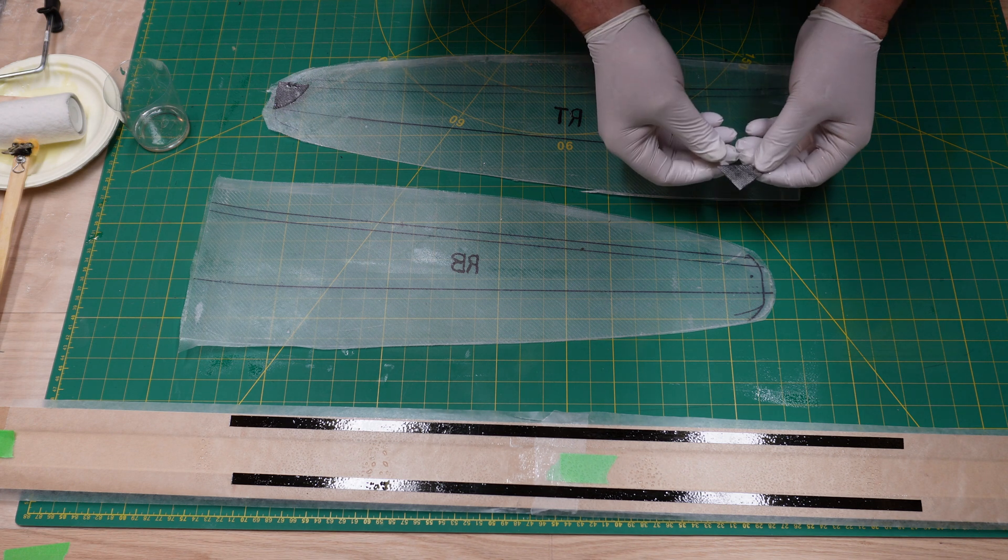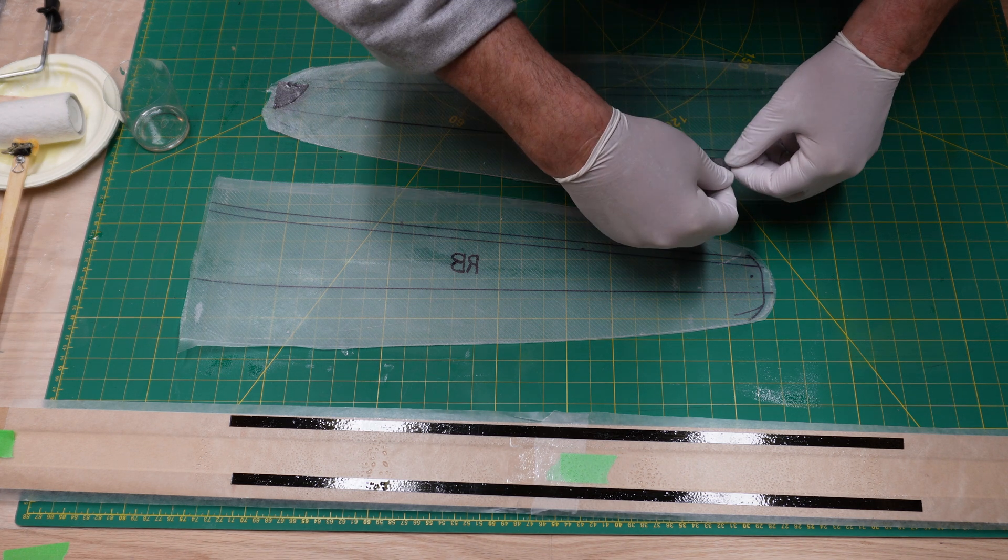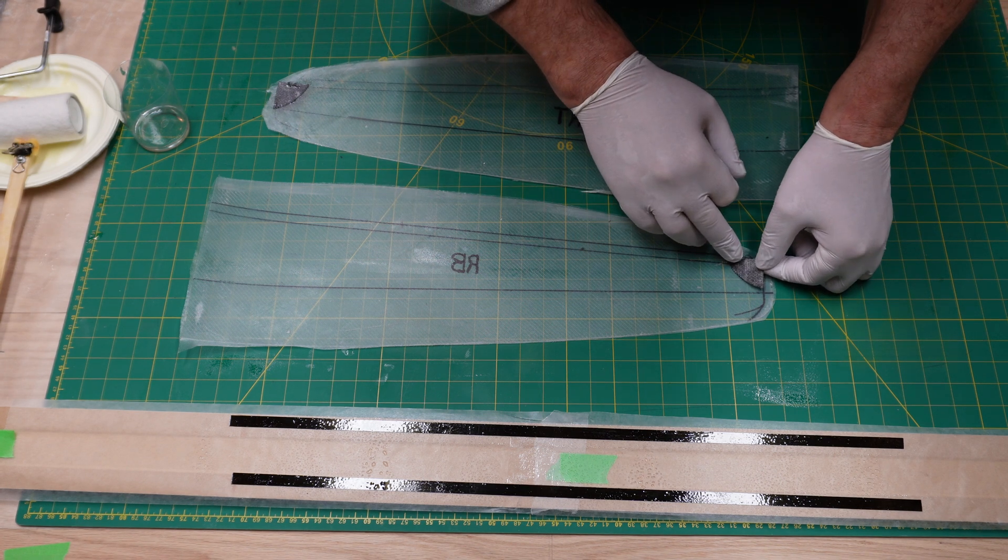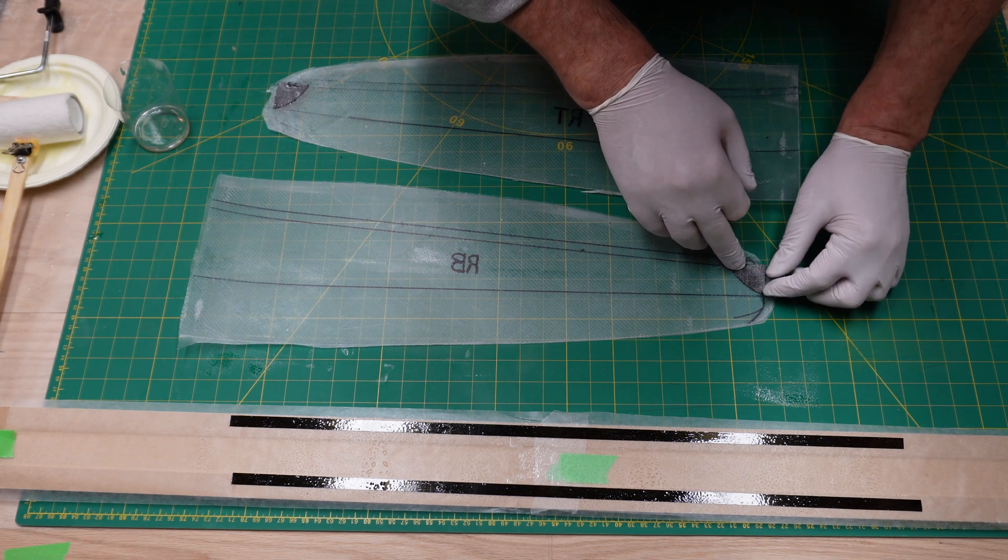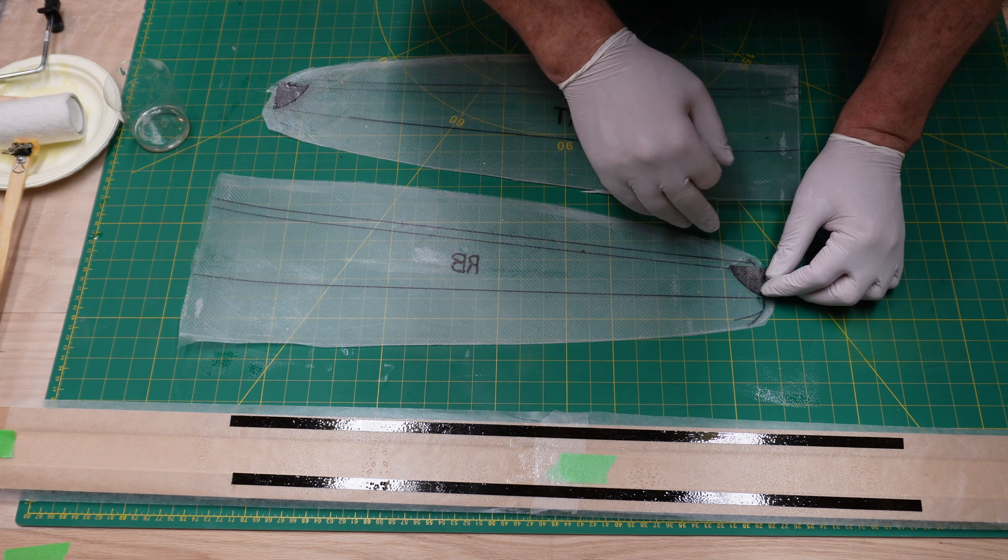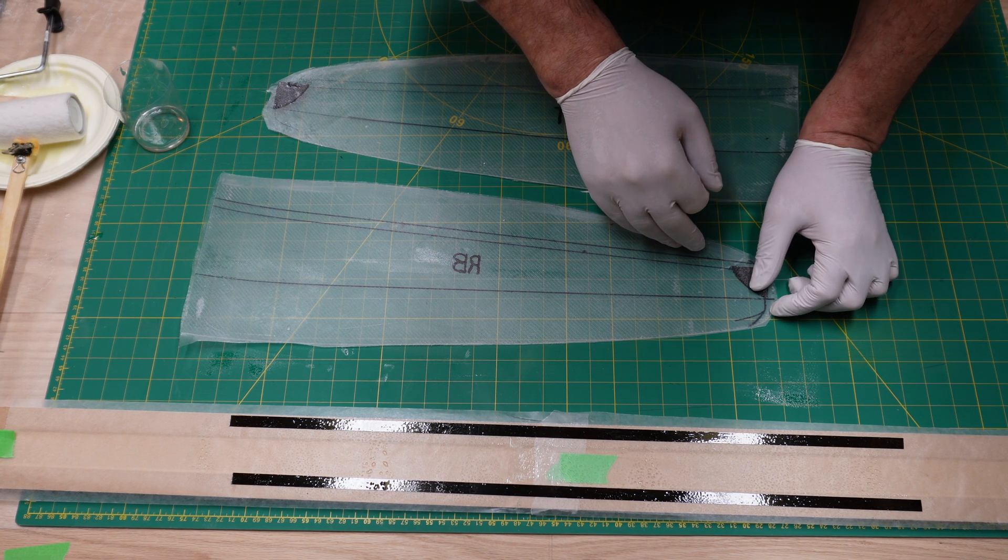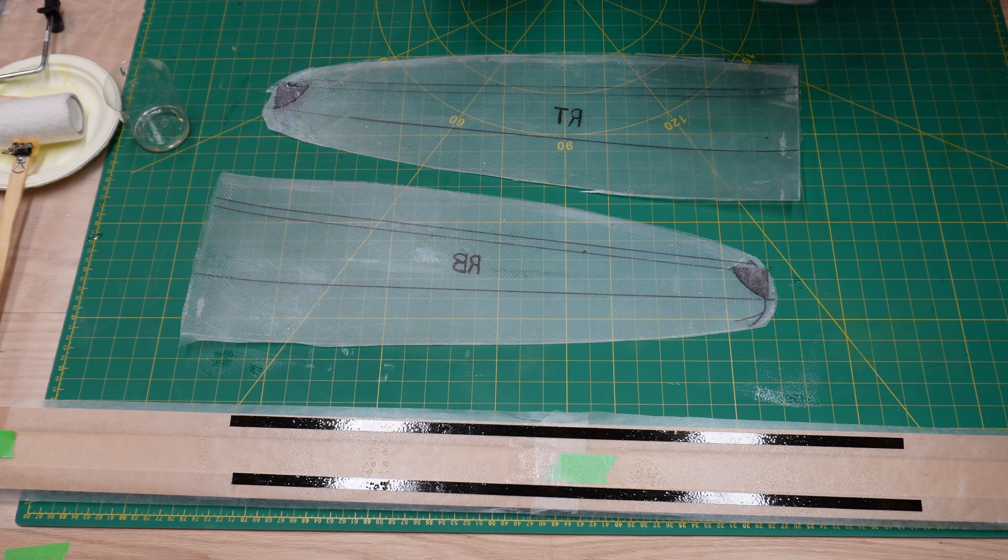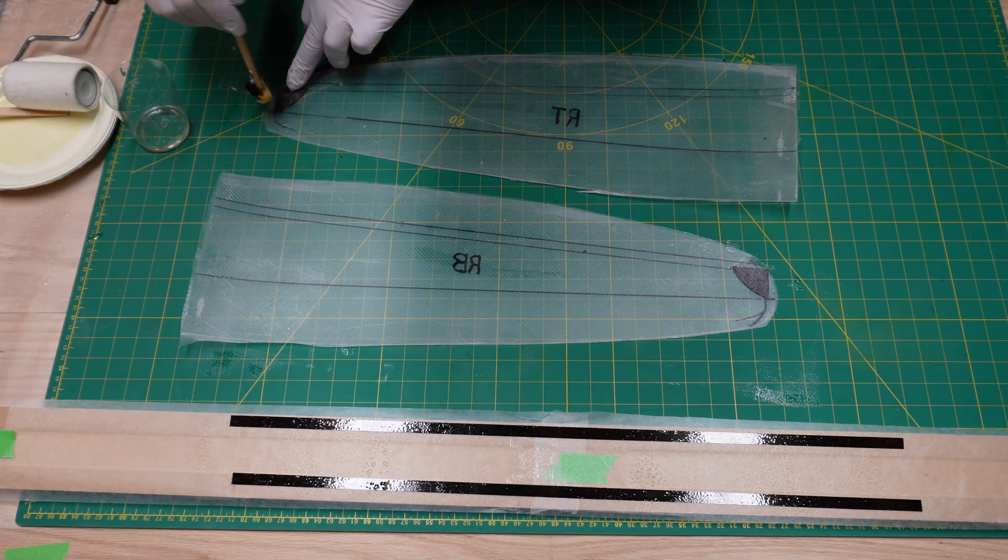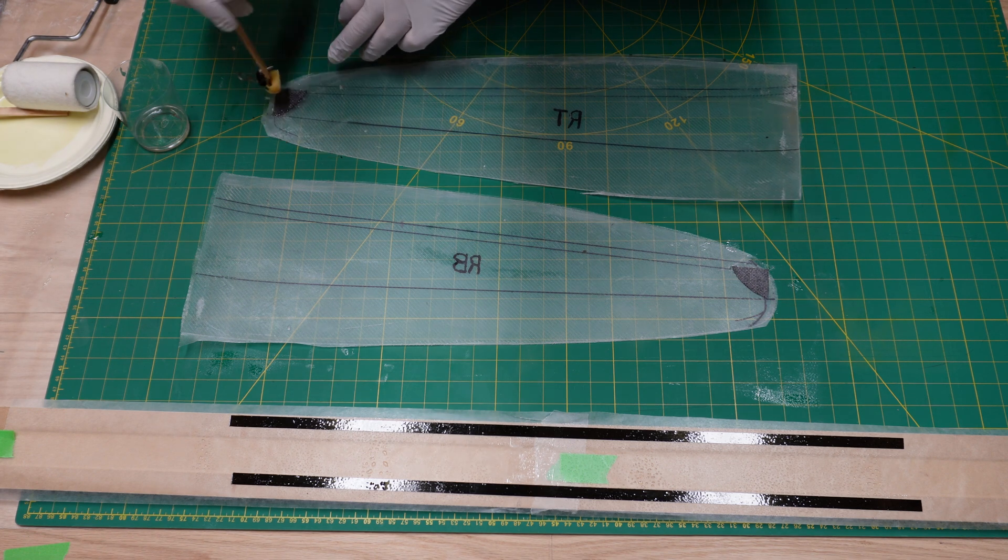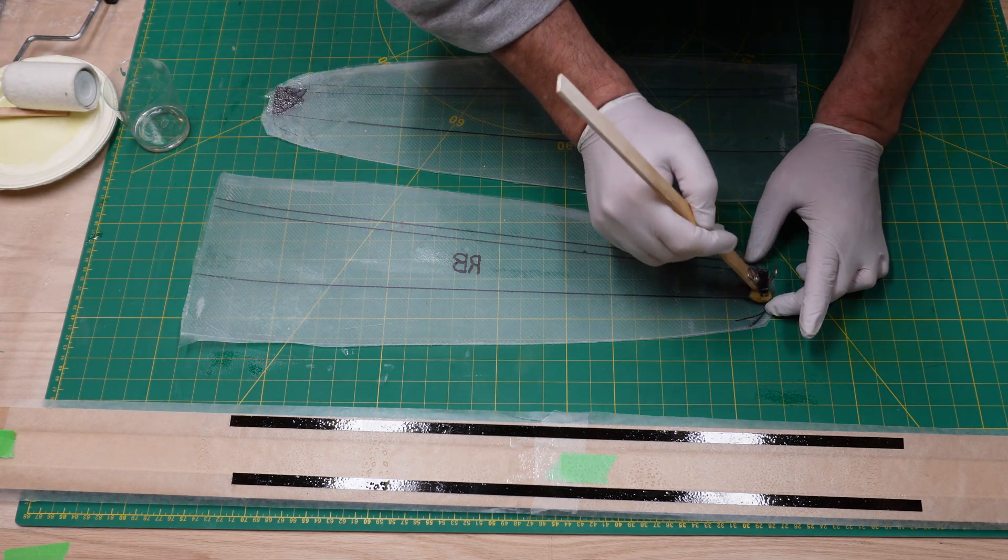I want to place it so it overlaps the spar and it's gonna sit over top of the leading edge 12K tow, so all three are joined as one. You're gonna have a really strong joint right there, and that's what you want for the throwing peg. We're just gonna wet it up a little more on the back side where the fiberglass is.